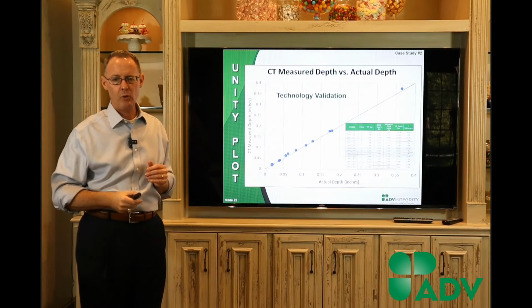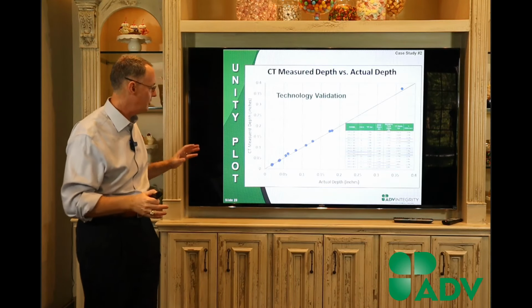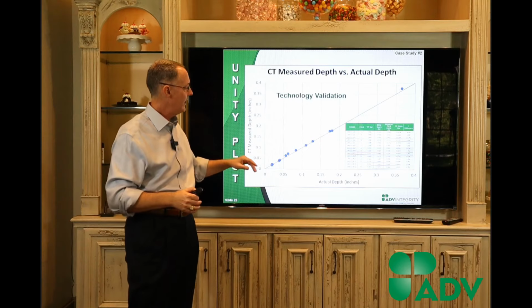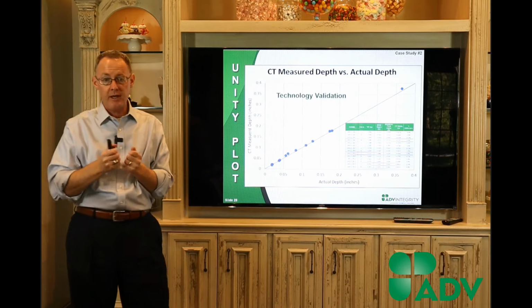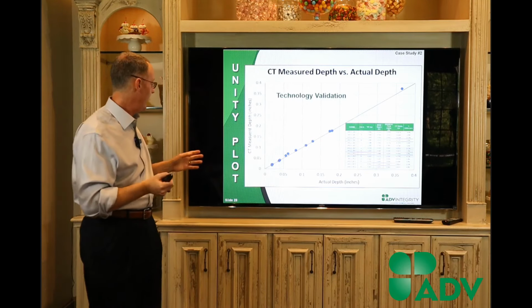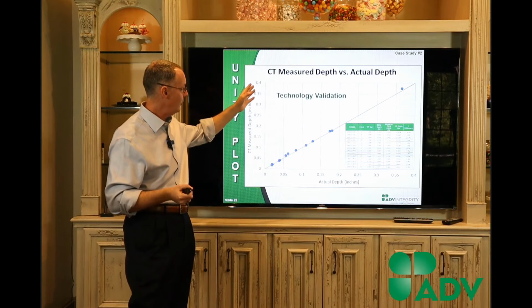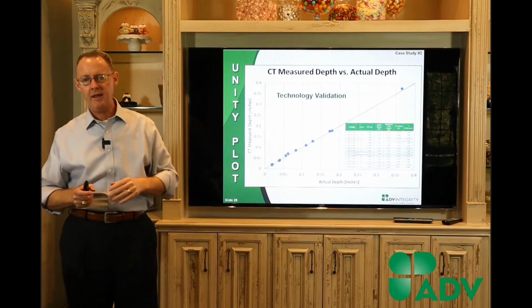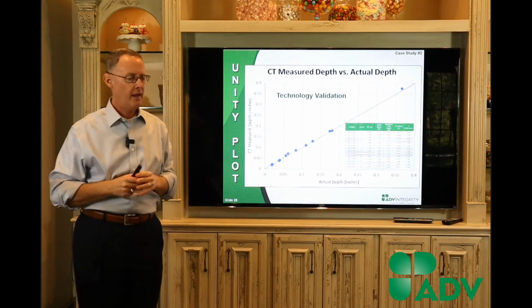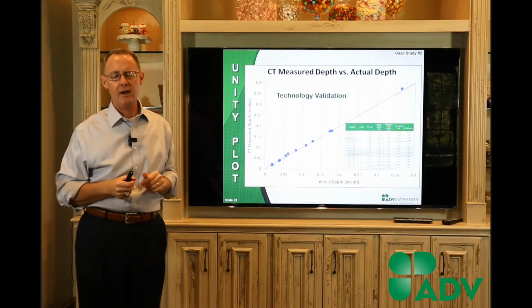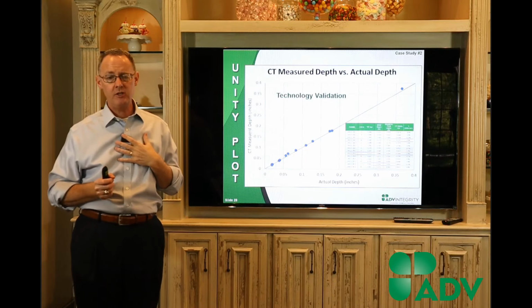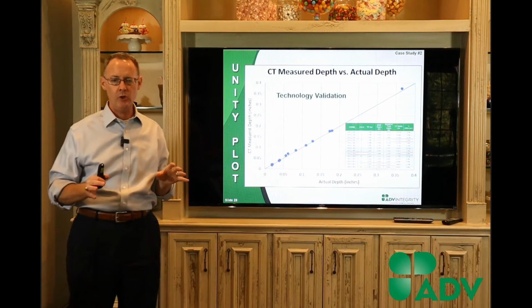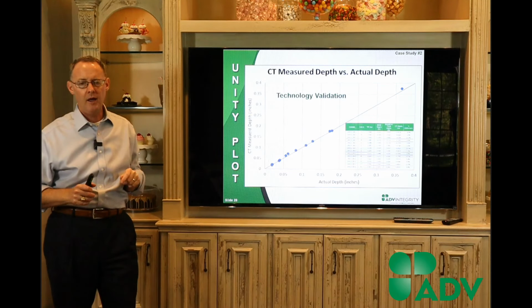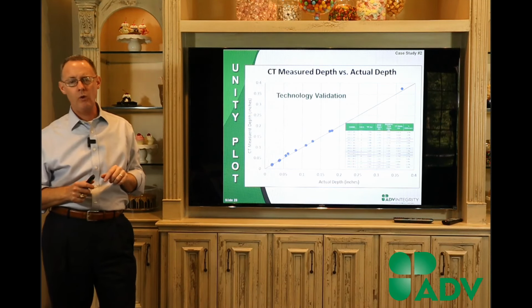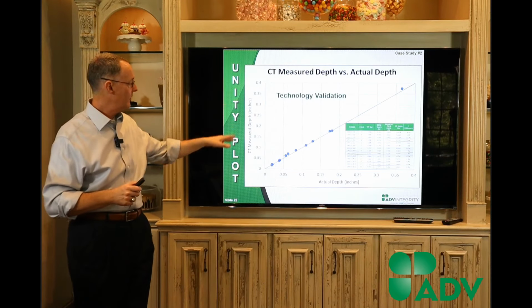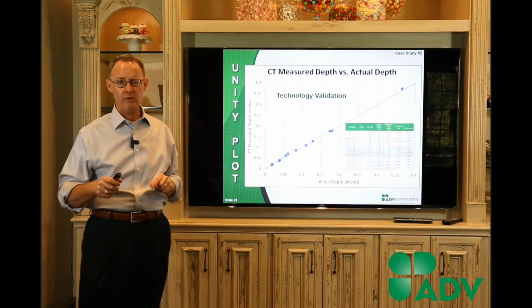So we're just doing a side-by-side comparison. It's kind of like Consumer Reports. We're comparing all the data. So what you notice here in this plot is the actual depth is what we measured once we cracked it open compared to the CT measured value. And a perfect set of data, it lines right on top of that line. And I could have put error bars and those kind of things on it. But my observation, based on a very simplistic view of the presentation of the data, is it's worked very well. There's a lot of good accuracy that we're seeing with that data.